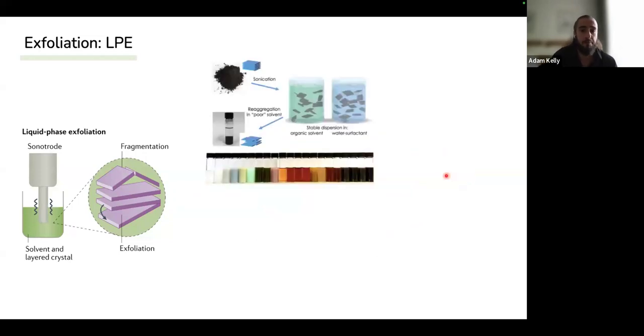So we do this with a powder. We apply this sonic energy, and then at the end of this process, if we choose our solvent well, we will have a stable dispersion. But if it's a poor solvent, for example, if you try to exfoliate graphite in IPA using this method, what will happen is it will all just reaggregate. So we need to match the parameters of our crystal with the parameters of our solvent.